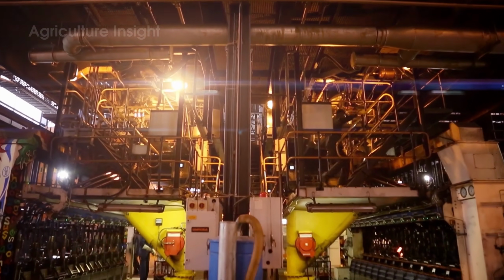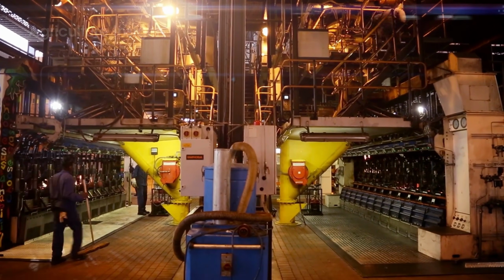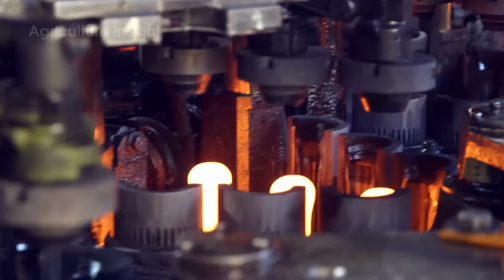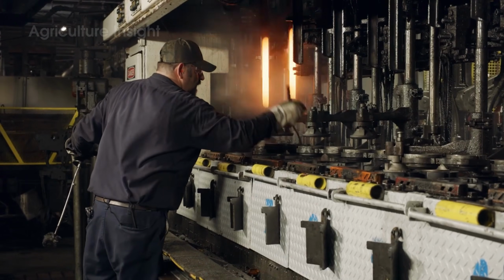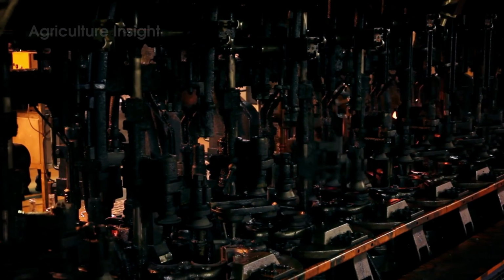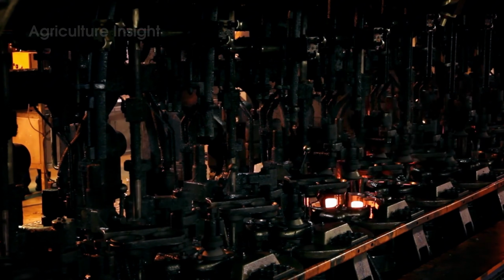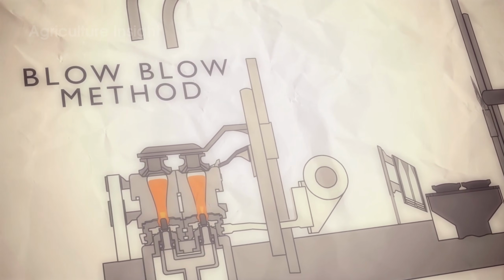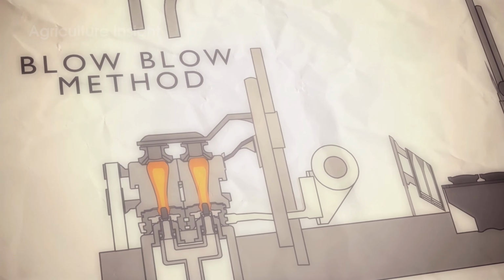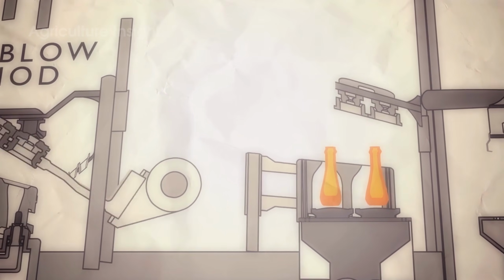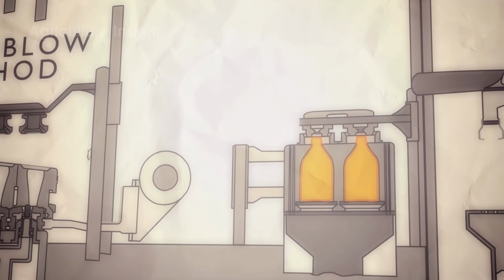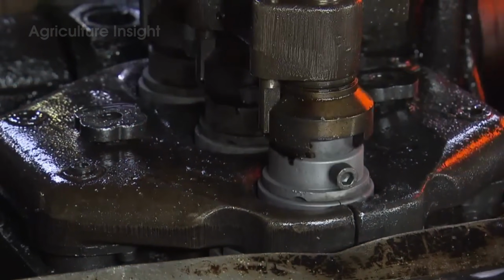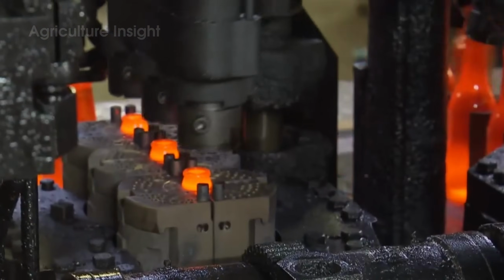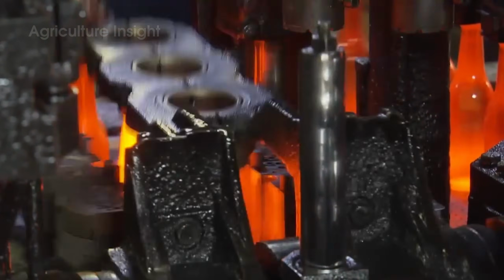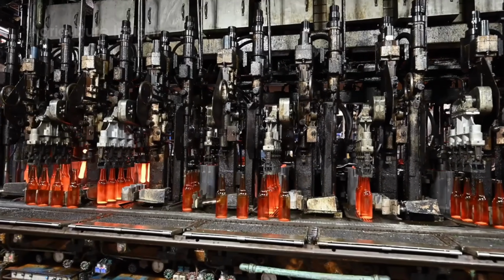When the mold system is ready, the process enters the double blow stage, the standard method for producing hollow containers such as soft drink bottles or pharmaceutical jars. The process begins by cutting the molten glass stream into gobs of uniform weight. These gobs enter the preliminary mold at around 1,000 degrees Celsius, the ideal temperature at which glass reaches stable viscosity, allowing smooth forming. Inside the preliminary mold, a first blast of compressed air is blown forcefully from above, pressing the molten glass tightly against the mold walls. The result of this step is the formation of a parison, a hollow structure in which the bottleneck is clearly shaped, while the body remains soft and retains a large amount of heat.